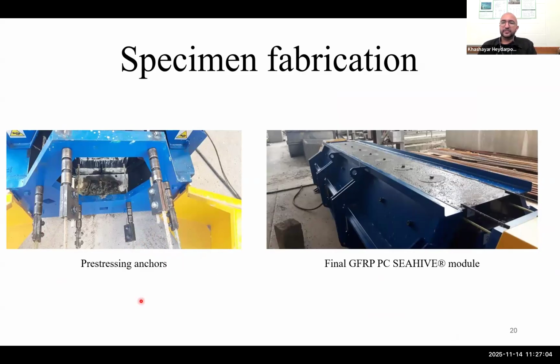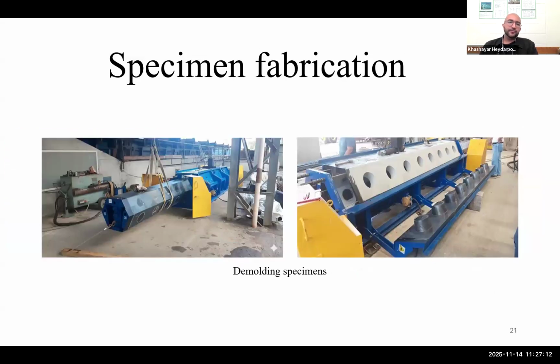The anchoring was done to make sure that the pretension remains in the specimen until the concrete hardens. And after 24 hours, rebars are cut and the demolding begins. And the specimens are ready to be tested.